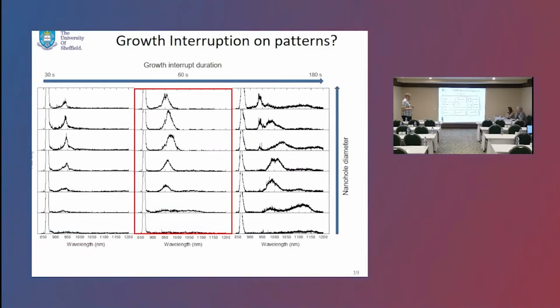So if we look at what happens on patterns, this was the panel we saw before where the size goes up and then appears to come back again. And if we concentrate first of all on small holes, so on small hole sizes we see kind of what we expect with the effect of the interrupt, that they move to longer wavelength, that we must be pulling more material in from the surface. And if we go to the sort of larger holes, we actually see a fairly stubborn peak that doesn't seem to want to move. And there, possibly it's getting narrower. Possibly what's happening there is this exchange of material between the dots and ending up with these 2 dots in the pit. So we can't go too large, even though we're kind of staying at the same wavelength, because 2 dots in your emitter is a problem.